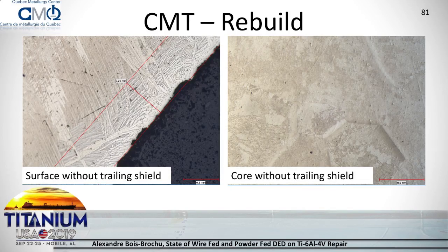No need to repair with TI64 under a full bubble protected by argon, which is not the case with powder fed. Since powder has an enormous surface, it's much more reactive, and you need to be under atmosphere.